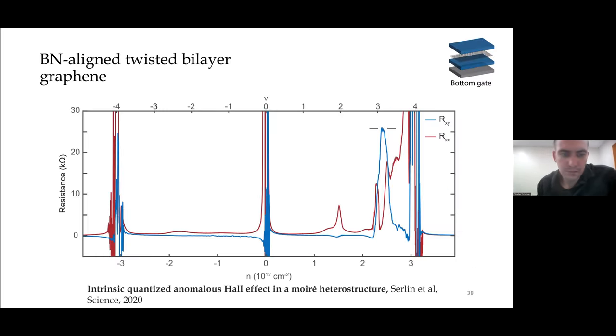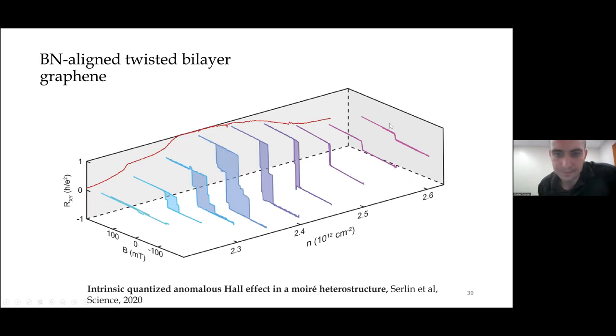So on the x-axis, I'm showing you density of electrons in the moiré superlattice that I just showed you. On the y-axis, I'm showing resistance. At full filling, which is 4 electrons per unit cell, and full depletion, we see large gaps. At 3 electrons per unit cell, we also see a dramatic drop in Rxx and a quantization of the Hall resistance. And this is this quantum anomalous Hall state that I've been discussing.